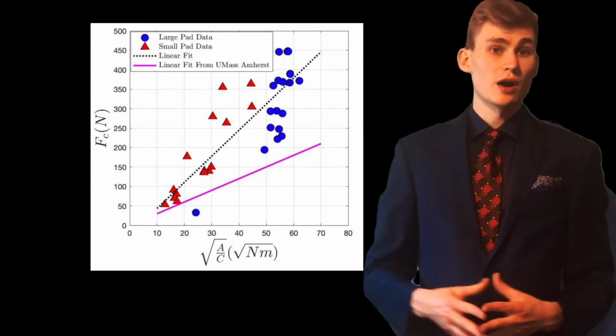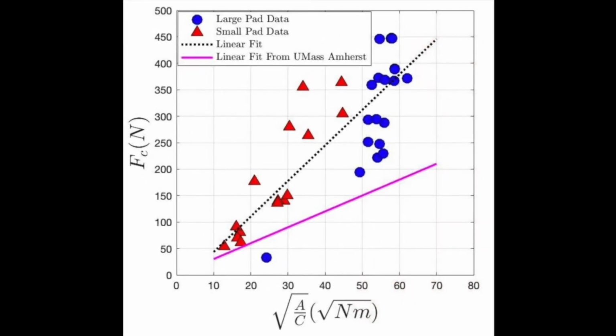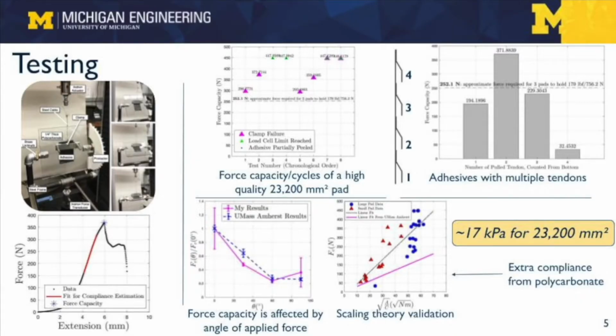I used polycarbonate as my loading surface, and they used glass. Polycarbonate is a significantly more compliant material, thus the compliance that I have measured is actually higher than the actual compliance of the adhesive. So the horizontal coordinates on this quantity of square root of the area over the compliance are actually smaller than they should be were I actually measuring the compliance of the adhesive. So the slope should be lower than it appears here. However, I haven't done anything to account for this, so this is just a hypothesis.